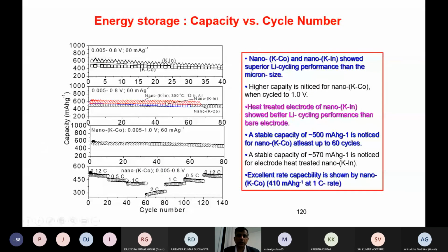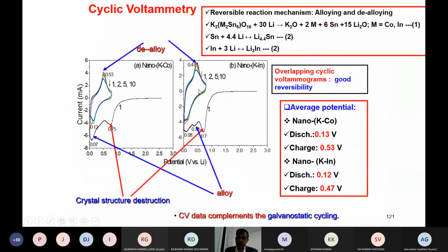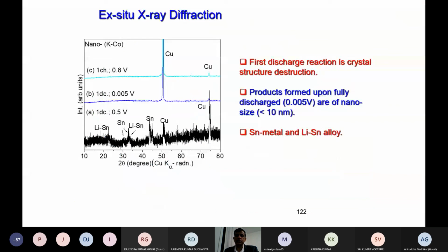Interestingly, for example, the cobalt and indium containing samples show reasonably good performance. The nano size seems to be a little bit better performing material when compared to the bulk material. Alloys are very important, so you have to think about good applications with lower and higher voltage reversible peaks, and the voltage should be lower. If you want to use it for energy applications, make sure the material has low potential and reversible peaks for real applications.